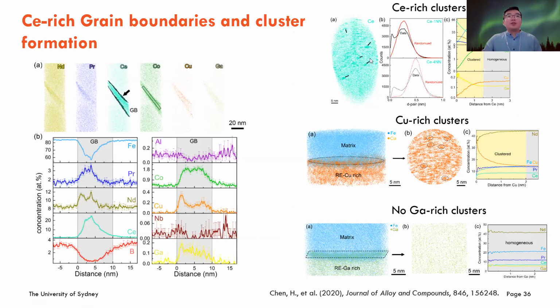And when we dug through, we found a new type of grain boundary, which is majorly enhanced with cerium here. And you can also see some interesting segregation on this interface, like the copper here. Copper mostly segregates on the interface between the matrix phase and the grain boundary phase. And that's the merit of the atom probe: you can know exactly where the atoms are.